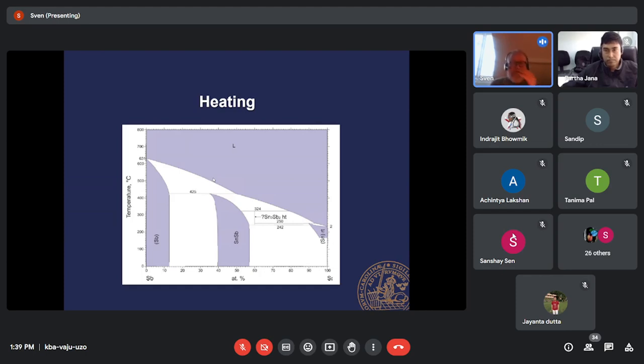So it's difficult to see the difference between tin and antimony. The reason we saw a superstructure in stistaite is not that we really see a big difference in scattering from antimony and tin, but that we see a difference in interatomic distances, which makes it possible for us to identify what is antimony and tin.